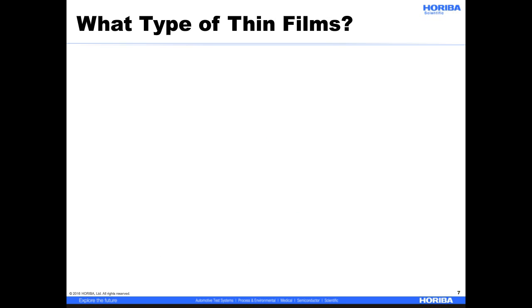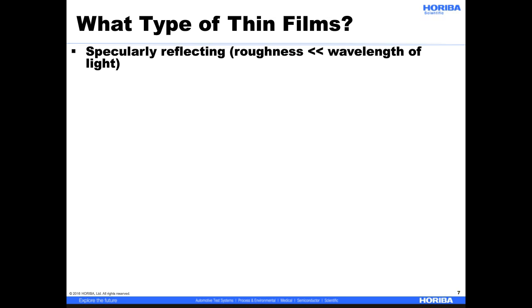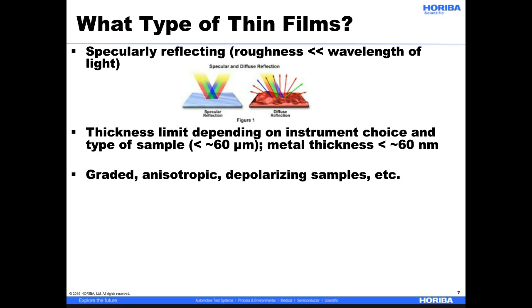So what types of thin films can be used for spectroscopic ellipsometry? Most of what I say here is dependent on the system that you have, so it can really vary from system to system. But in general, you want specularly reflecting samples where the roughness is much less than the wavelength of the light. You have a thickness limit that ellipsometry can determine, and that again depends on the instrument choice and the type of the sample you're working with.